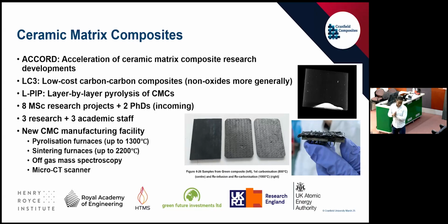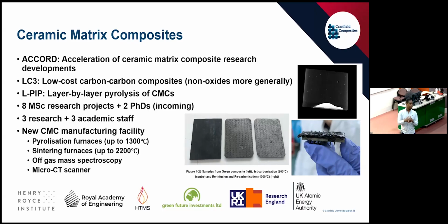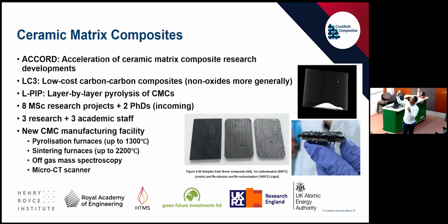I think this year we have 4 MSc projects with them, 4 MSc students, looking at this interface between the silicon carbide and this tungsten, using through-thickness reinforcement to better transfer the heat between the materials as well as provide the adhesive bond. What you get effectively is, when you run the simulations, the stresses are absolutely massive. They're gigapascal stresses, but they are compressive. So what you get is compression around the pins, which keeps everything in place, which is quite clever and quite useful. But also, what happens on the back surface when you have these high temperature corrosive salts running around?